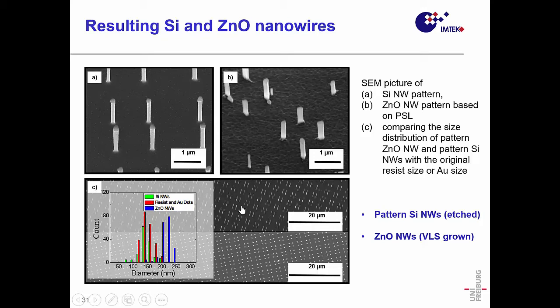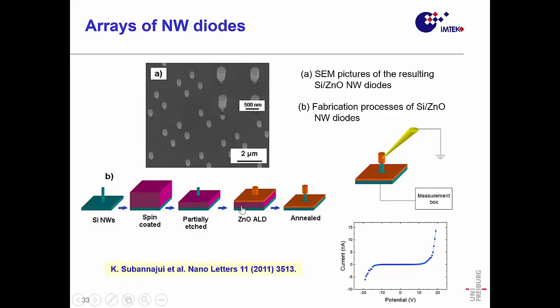For the growth, you have to optimize it. It's not completely optimized here. We can do it better. For the silicon etched ones, the fitting of the diameter to the etched one is better. For the grown one, we have again the shift to larger size for the nanowires, but you can do that on large scale, and then you can use that for a number of things. You can go for diodes, that's etched silicon nanowires overgrown by ALD, and then have some devices here.